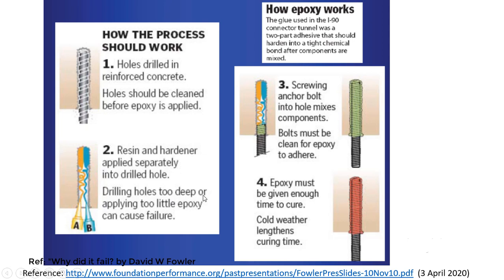Drilling holes too deep or applying too little epoxy can cause failure. So again, this hole should not be drilled too long, otherwise the epoxy will not go all the way to the end of the hole. And applying too little epoxy can also cause failure, because then you will not have good bonding between the concrete and the bolt.